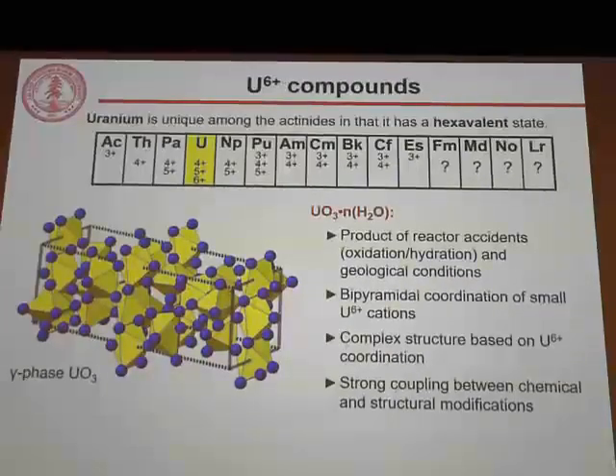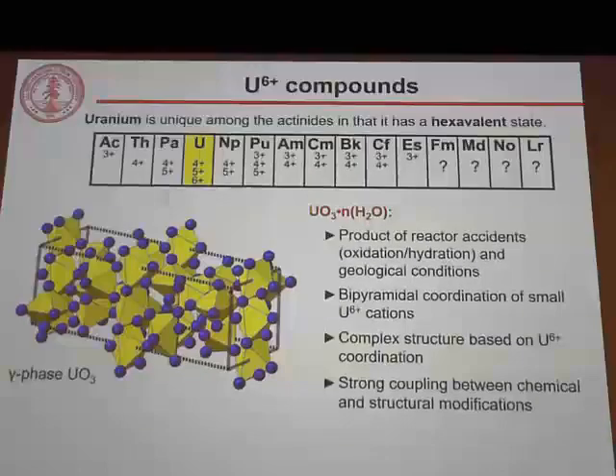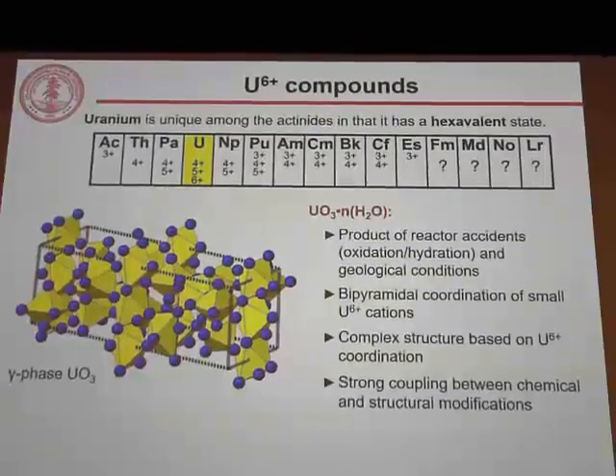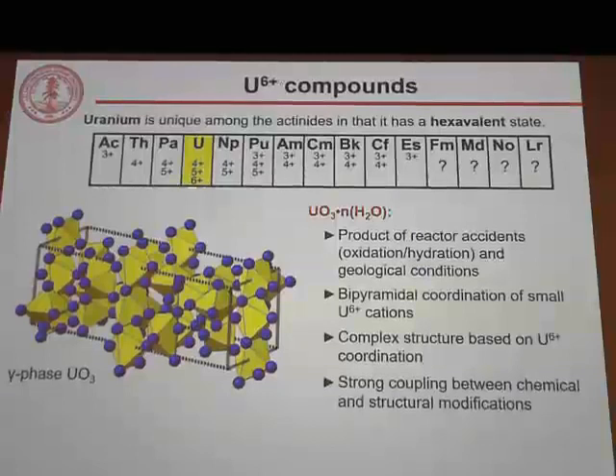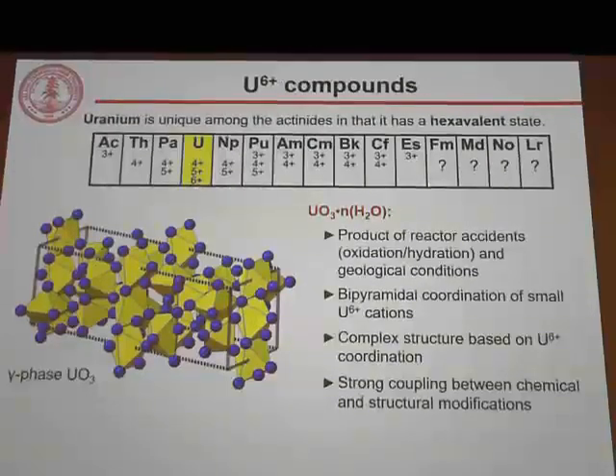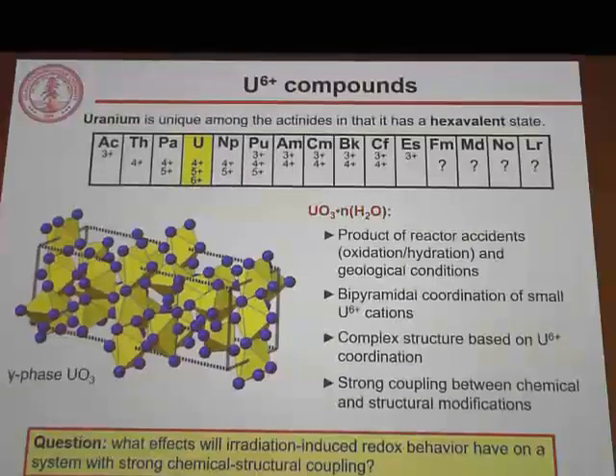Now these compounds have unique bipyramidal coordination of the very small hexavalent uranium cations. And what this results in are complex structures which are closely coupled to the specific hexavalent uranium coordination. And this results in strong coupling between the chemistry of these materials, the fact that they have hexavalent uranium, and their structures. It's such that we might imagine irradiation-induced reduction of the uranium would cause dramatic structural effects. So that's the question I was answering here.